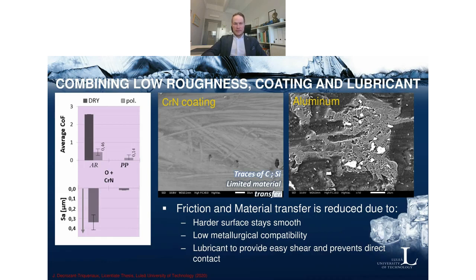When looking at the surfaces, this is quite clear: when you have post-polishing and lubricant, you basically have no trace of the aluminium on the chromium nitride coating. Literally no transfer at all. The lubricant works well, and there is no mechanical pickup. There is an interaction of the lubricant with the aluminium also, so it forms a tribo layer on the aluminium, which is an interesting aspect in itself, and cleanability comes into the picture when that happens. But that's a separate study that we are also working on.